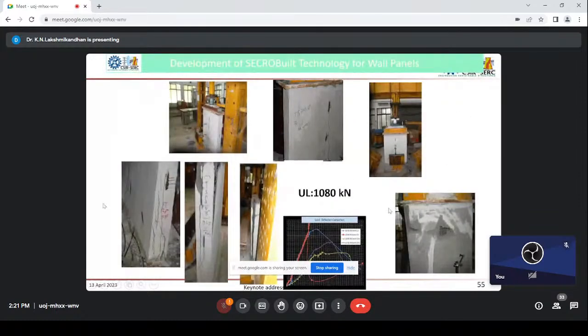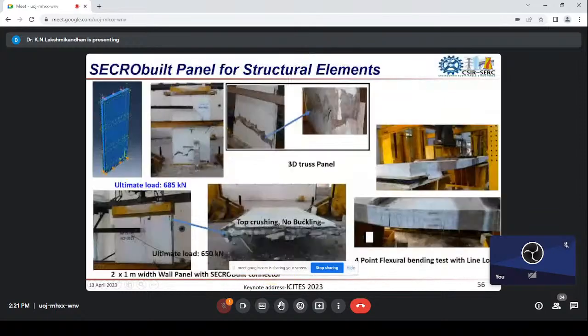So these are the failure patterns. Without any interfacial connector, it will fail at the ribs and then debond. As a result, the load will come down. When you come to an interfacial connector, there is a shear interface connector between the two skins. Then the load carrying capacity is very high, only local crushing is happening, and everything else is intact as a unit. You see that everywhere only the local crushing is happening, and the entire system is intact.